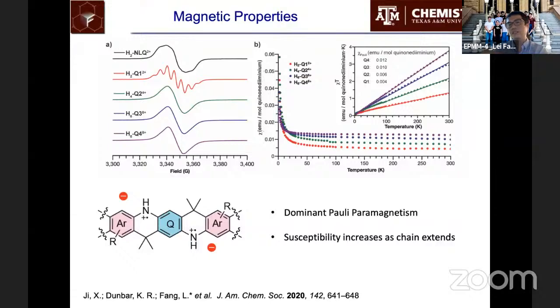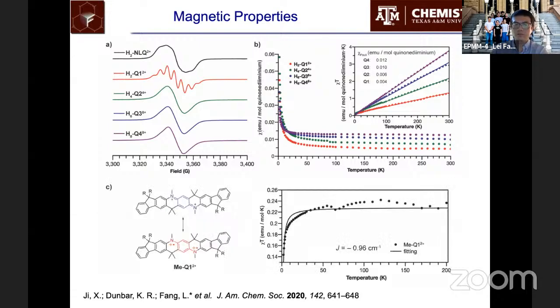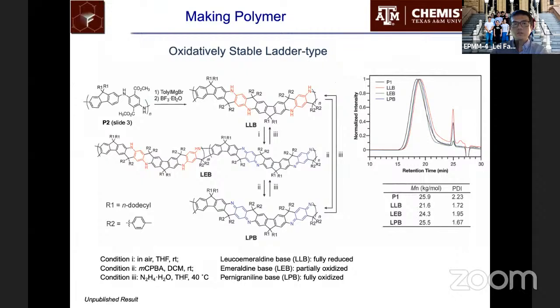And so this is indicating that the compound should intrinsically be conductive, which is a little bit debatable before we publish this work. The polaron delocalization, we believe, is strongly correlated with the proton in this case. We also made a polymer version of this compound with molecular weight about 25 kilograms per mole.